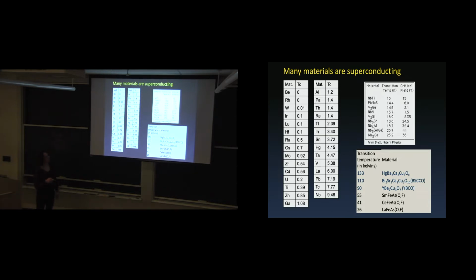Then there's the alloys, things like niobium-3 tin, which is used in MRI magnets. That superconducts at higher temperatures, but also can withstand very high magnetic fields, so it's good for magnet wire. And then there are the high temperature superconductors, things like YBCO and BSCCO. These superconduct at 90 Kelvin, which is important because it's above the temperature of liquid nitrogen. And liquid nitrogen is much less expensive than liquid helium.